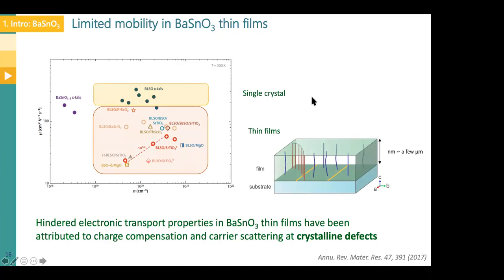Now we thought, okay, we know these crystals could have line defects in them. We know they're going to have dislocations in them. Dislocations are the most common line defects. They occur inside of the crystal and on the grain boundaries. But we want to see if there is more to it than dislocations. So the crystals were grown by using molecular beam epitaxy.